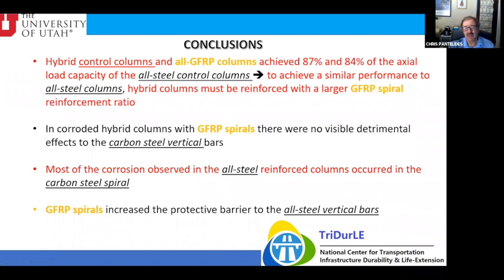So for corroded hybrid columns with GFRP spirals, there were no visible detrimental effects to the carbon steel bars. Most of the corrosion observed in the all steel reinforced columns occurred in the carbon steel spiral. So the fiberglass spiral increases the protective barrier to the vertical steel bars. And it goes like this: if your spiral, which is on the outside of the reinforcement, doesn't corrode, then how are the chlorides going to penetrate and find the vertical steel bars? It makes it more difficult.